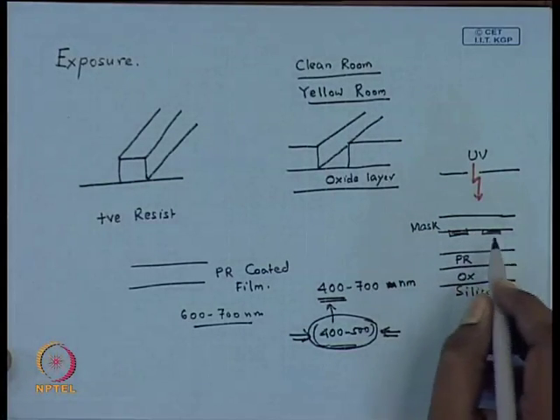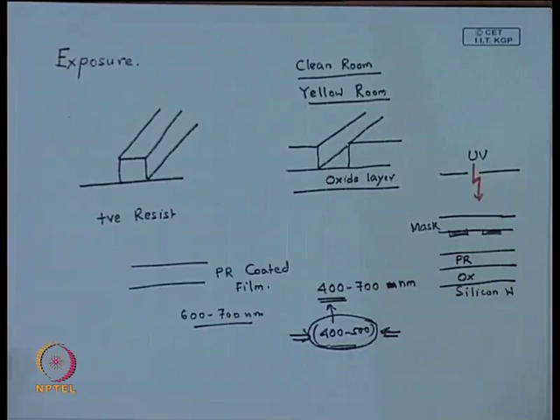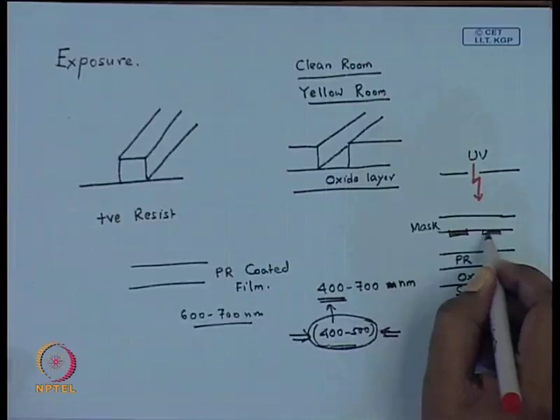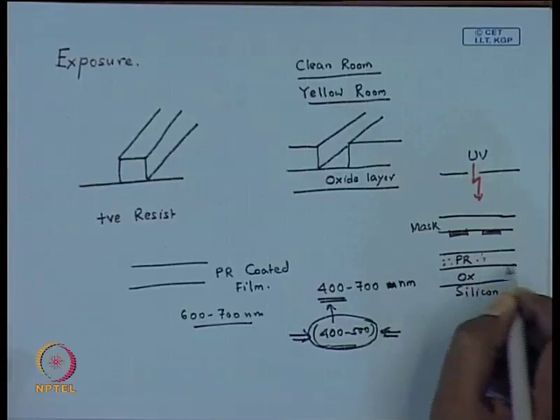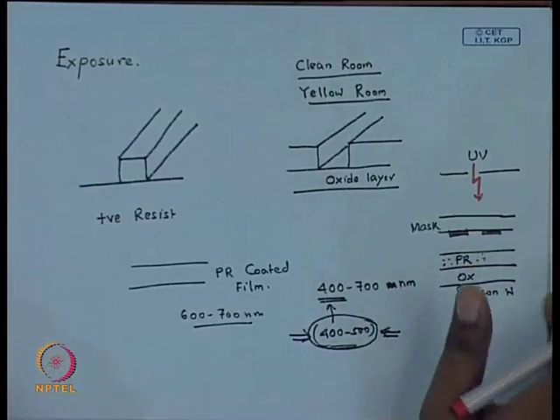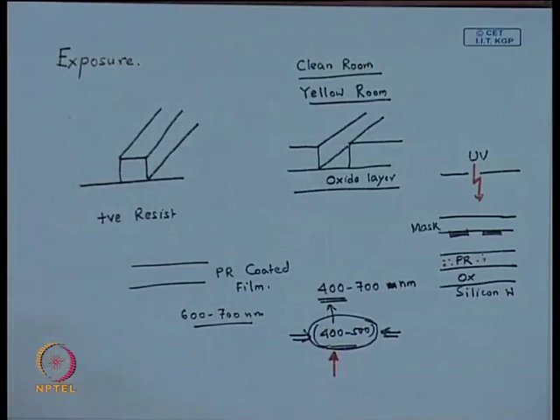The issue is that if you move around with your photoresist coated wafer in white light, even before you do a proper UV exposure, part of the photoresist will cross link or degrade, and this is independent of the location of the mask. Even though you expose later under a mask, this photoresist layer is not pristine, but has already undergone some structural changes because of unwanted photochemical reaction of the components of white light having wavelength in this range with the sensitizer part. That is why most of the photolithographic steps associated with the microelectronic industry or other processes are invariably performed in a yellow room.